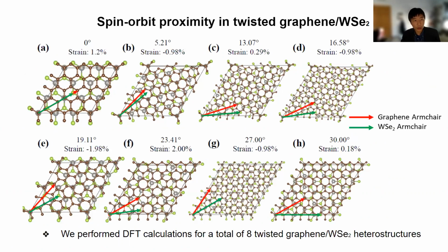The first thing that we do is look at the band structure of this bilayer system. So we have graphene on TMD, and we look at different angles. The first thing that we have to calculate is the band structure using DFT. But to compute the band structure, we first have to define a supercell. And to define a supercell, we have to force the two materials to be commensurate, and that will incur some strain because the lattice constants of the two materials in general are not the same.